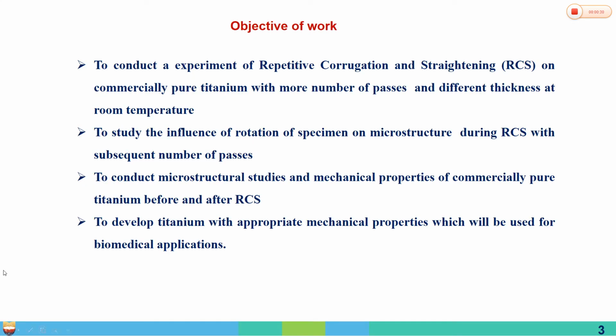The objective of this work is to increase the strength of commercial pure titanium to be equal to the strength of Ti-6Al-4V by applying severe plastic deformation techniques like repetitive corrugation and straightening. We ensure the strength by measuring the hardness of the material, and we also study the microstructure of the material after RCS with the number of passes.